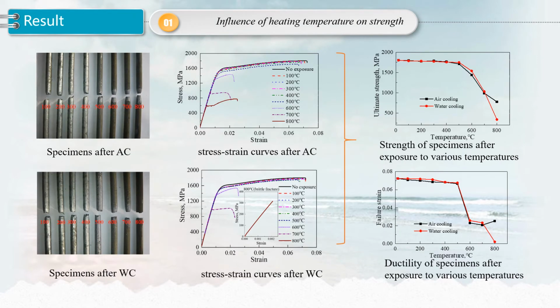To study the effect of heating temperature on property of steel wire, the specimens were heated to different temperatures ranging from 100 degrees centigrade to 800 degrees centigrade, and 2 cooling methods, air cooling and water cooling, were investigated and compared. The air cooling method is to simulate the natural extinguishing of fire, and the water cooling method is to simulate the fire being put out by a fire engine.